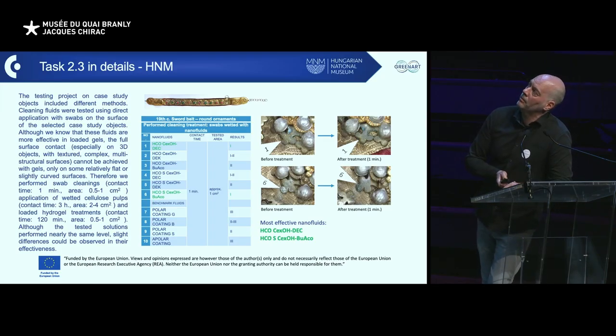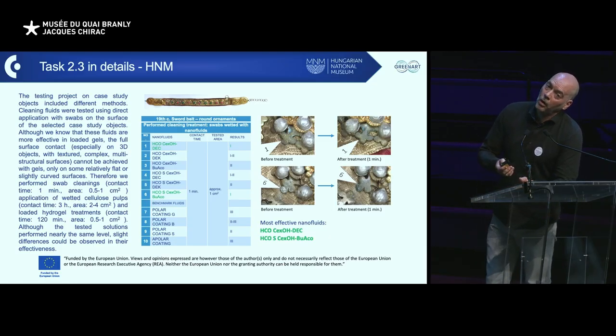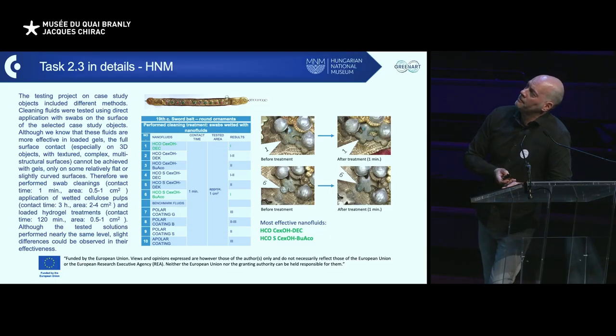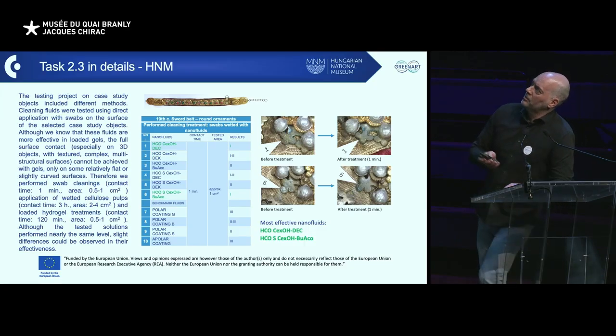First, we tried the cleaning fluids on the nobleman's belt, and in this case, because of the complex structure of the surface, we did not use the gels. Instead, we tried the nanofluids with swab cleaning, and in this case, two of the nanofluids were effective. We could observe the diethyl carbonate and the butyl acetate types. Maybe you can see, not so clearly, the differences before and after treatment of 1 minute. And of course, these materials removed this grime dirt layer, but also some of the corrosion products which were embedded in this grimy surface contamination.